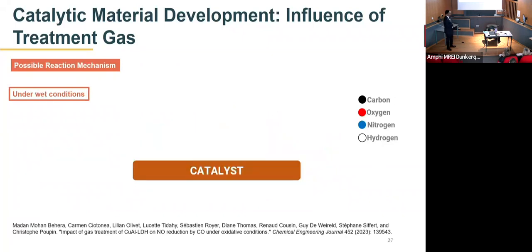Under the wet reaction conditions, there is something interesting happening that we propose. At first, there is the adsorption of the water molecules on the surface of the catalyst. The CO molecule that is already in the adsorbed state can react with the water molecule to form the formate species, and this formate species can decompose to form the CO2, and there is a formation of an hydrogen,